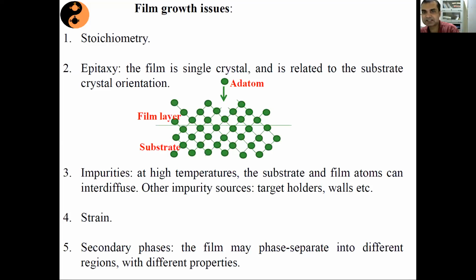Okay, strain is another issue. As I said, that since the grown film tries to adopt the crystal structure as that of the substrate, then it can have a strain. Either your film unit cell can be slightly larger than that of the substrate unit cell, then in that case the substrate will pull force to match its lattice parameter, so that it will have in plane compressive strain. If your substrate unit cell lattice parameter is larger than that of the film, then substrate tries to stretch it to match its lattice parameter, then in that case your film will feel in plane tensile strain, right? So these are some of the issues.